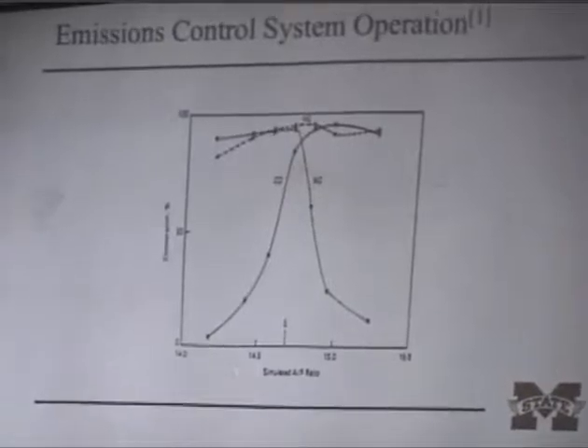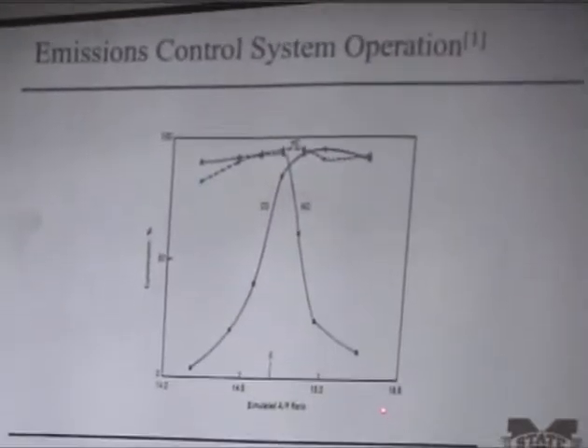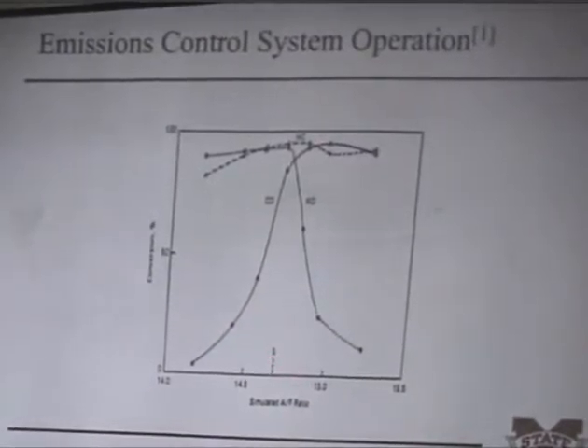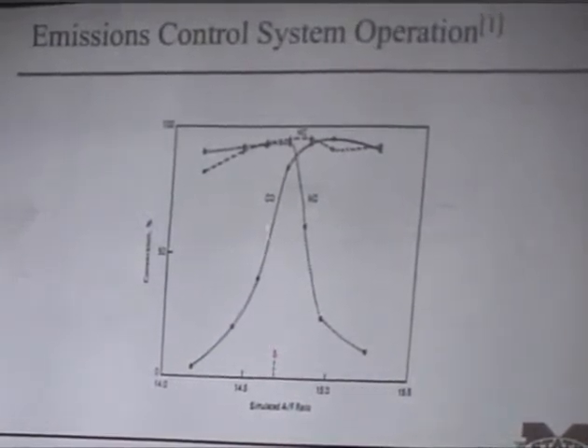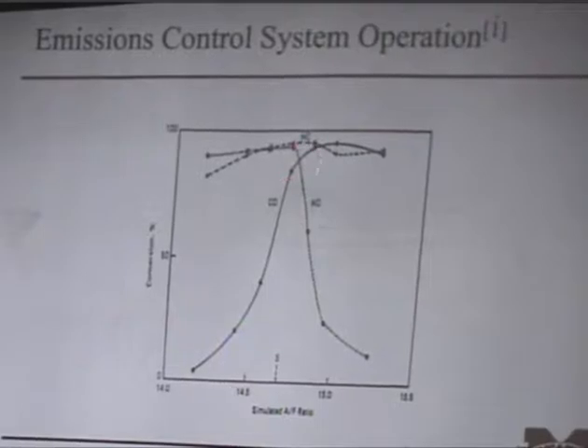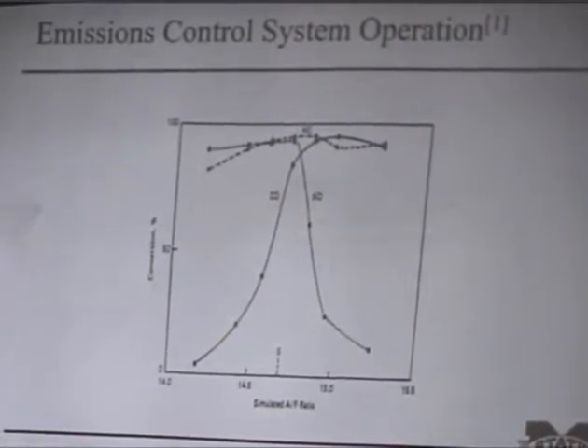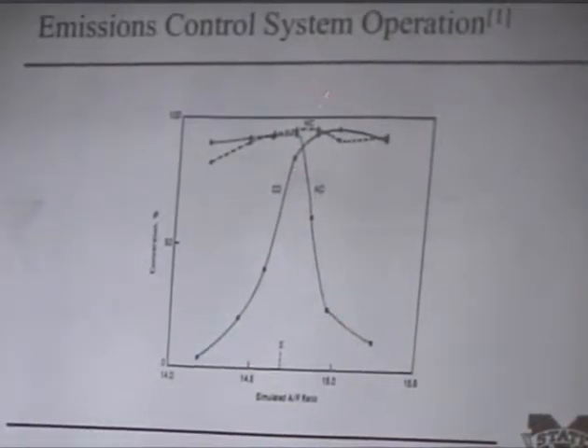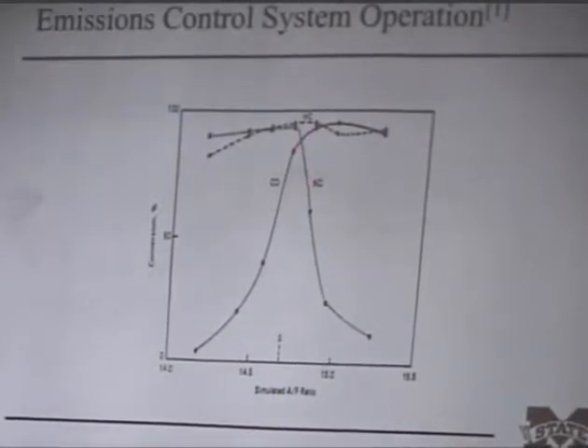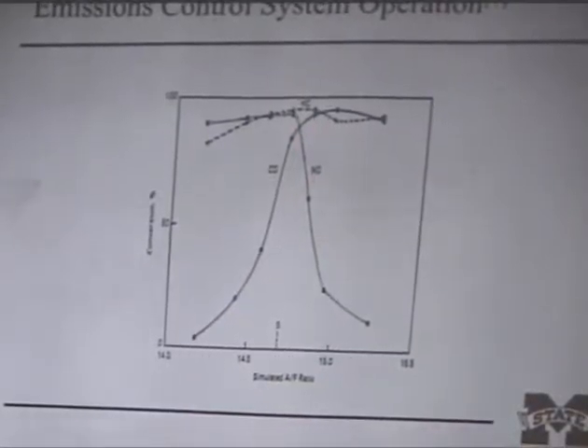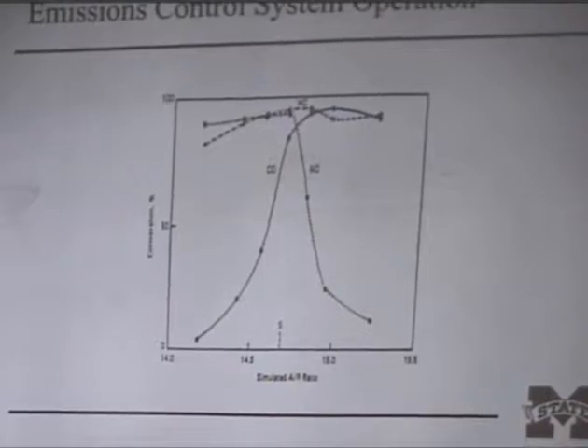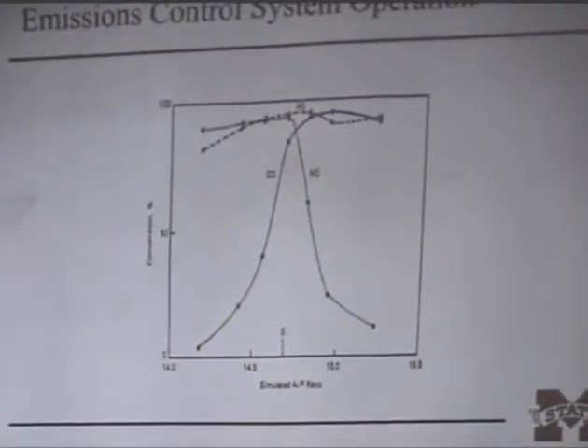What further complicates this is that most of you have seen these sorts of diagrams, where this axis is conversion and this axis is simulated air-to-fuel ratio. We like to operate right around the stoichiometric ratio, where we see nearly complete conversion of hydrocarbons, CO, and nitrogen oxides. The problem is that in an engine, we have periods of fuel excess and fuel lean, or oxygen lean and oxygen excess, depending on how you want to look at it.